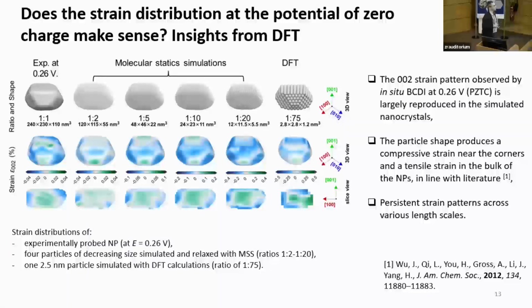So first, let me show you what we got at this potential of zero total charge. So already when the surface charge is like 0, you see that there is a heterogeneous strain distribution. So essentially, you get a tensile strain in certain parts of the surface. You get compressive strain in other parts of the surface. And well, does it make sense?